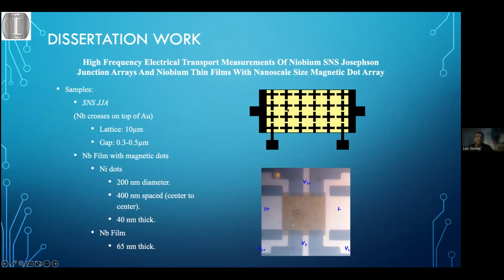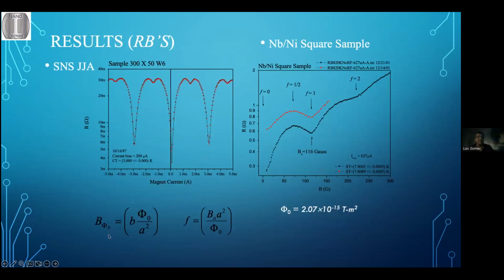So there is a correspondence between the area formed by this superconducting loop and the magnetic field. This is what this measurement shows: anytime there is a correspondence between the applied magnetic field and the flux related to the quantum flux that goes around the plaquette, that square, then we'll have a minimum. I was able to see that in the classical Josephson junction arrays, but also in the system with nickel, there was a dip, and I did some calculations.